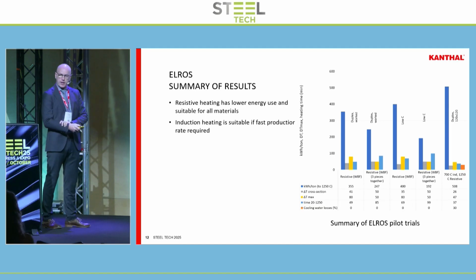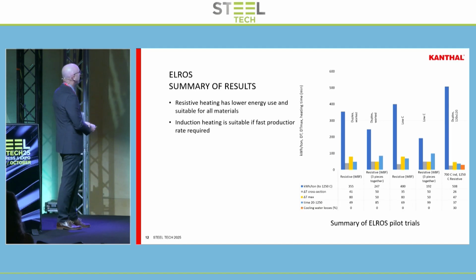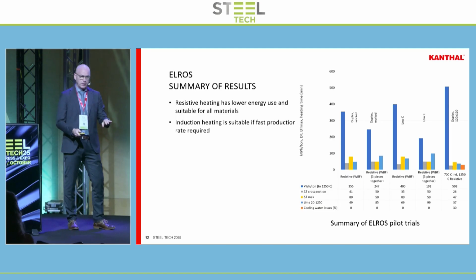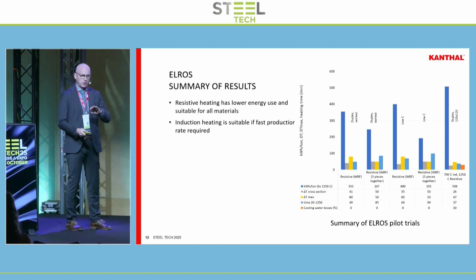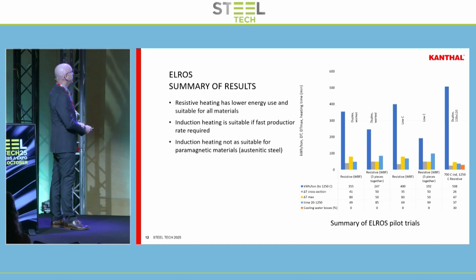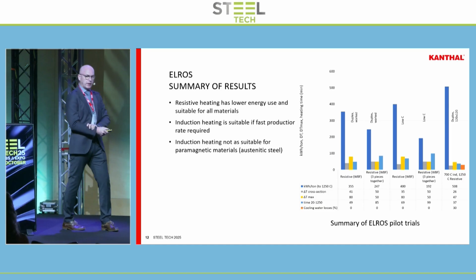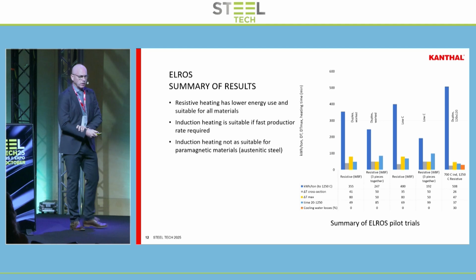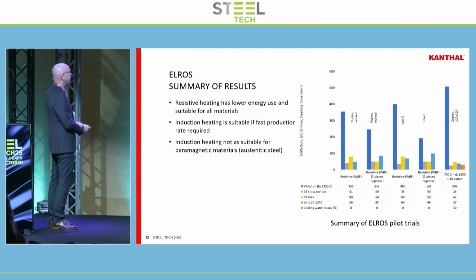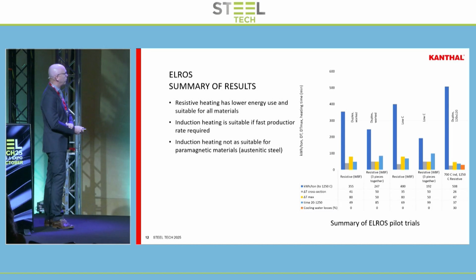Induction heating has its advantages for sure. And it's certainly suitable if you want a fast production rate, if you want a fast heating rate. Definitely induction has a clear advantage there, no doubt. Not as suitable, we found, for austenitic materials, where you take up that energy from the RF coil. But there are advantages to induction heating.